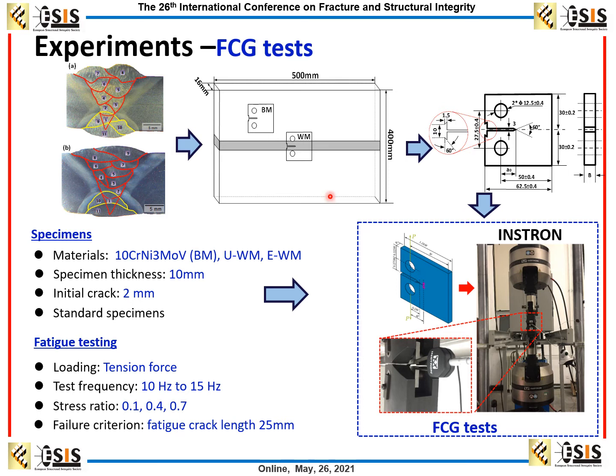The details by which the experimental investigation to characterize both the welded joint and the properties were conducted are as follows. It should be noted that the test frequency ranges from 10 Hz to 15 Hz for all the FCGR tests, conducted using several hydraulic controlled load frames. And three stress ratios are loaded in the test, and the crack propagation length of 25 is defined as the failure criterion. So this is the machine of the FCGR test.